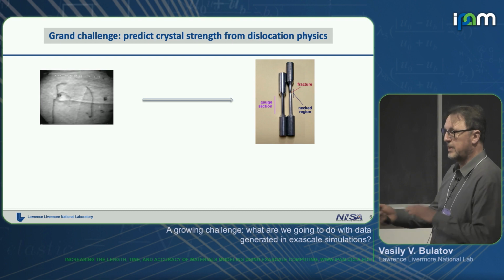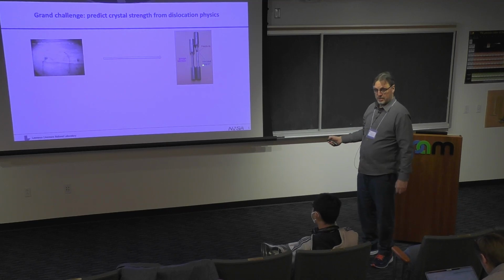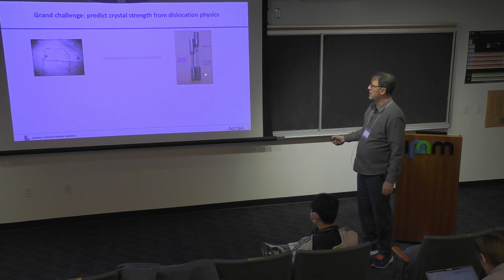As they move, they propagate slip. Crystal planes slip relative to each other. The crystal changes its shape, and then eventually perhaps breaks. And it is the behavior of these dislocations, their motion, that largely defines how much stress or load a material can sustain. So we need to get from here to there somehow.